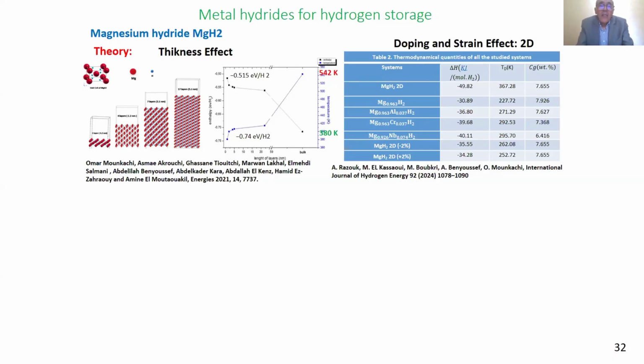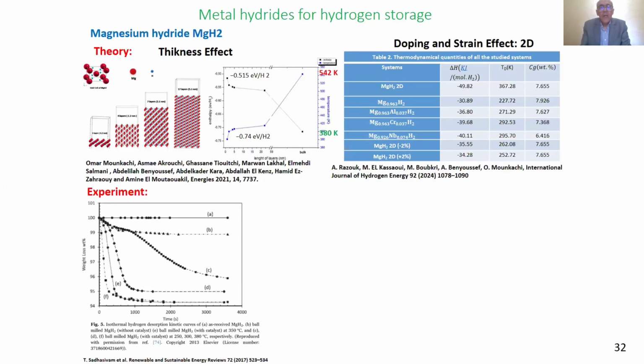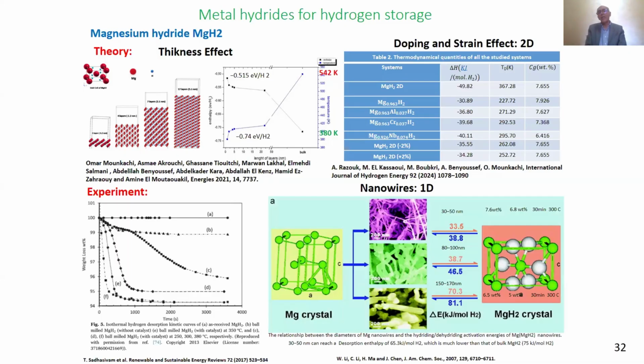By increasing the thickness, the performance decreases, but the best one is with the monolayer. And we can also improve the result by some substitution or some strain for both. The effect of size and dimension has also been studied experimentally. And it has been shown experimentally that with one dimension we can reduce the desorption temperature, improve the stability, and at the same time improve the time of absorption and desorption of the hydrogen from this material.